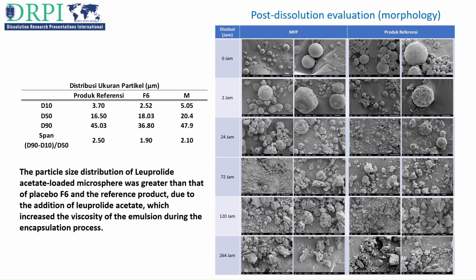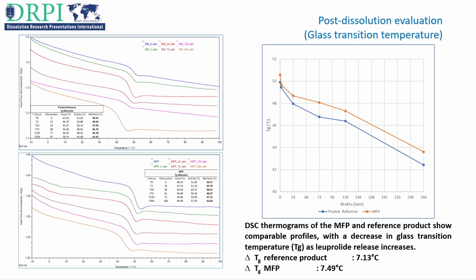Particle size distribution of leuprolide-loaded microspheres was larger than that of blank microspheres due to increased viscosity of the emulsion caused by leuprolide acetate addition. Particle size distribution of drug-loaded microspheres was larger than the reference product but still showed good similarity. Some images during in vitro testing also showed erosion and degradation profiles similar to the reference product.